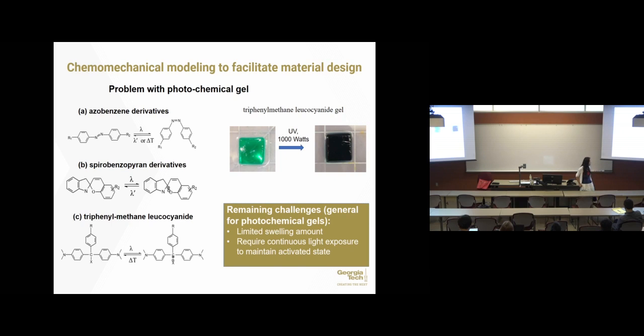And actually, there are reasons for that, because for most of these molecules I show here, the photo efficiency is very low. So you don't generate a lot of swelling ratio. That's one thing. Another thing is, in order to keep the molecule in the activated state, meaning keep the gel in a swollen state, right? You have to constantly keep the light source there. Otherwise, it will come back. So in certain applications, it's not desirable. So for example, you can consider you have a complex light pattern shined on the gel. And as you shine light to it, it locally deforms. And the material will generate a very complex global shape change. And then you lose track of where you wanted to activate the material, the pattern tracing.